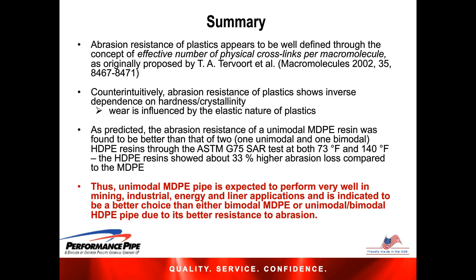So one question we got was about how particle size in the slurry affects the polyethylene pipe. In general, there are a couple of generalities that go along with particle size and hardness. The larger the particle size, typically the more wear we see on the pipe, and that's true up until a particle size of around 100 microns, and after that, the effect becomes negligible. Same goes with hardness. The harder the particle, the more the increase in the rate of wear on the polyethylene. Another one is the shape of the particles. The more rounded it is, the less wear it creates on the pipe, while the more sharp angular solids can gouge the material more and create more wear.